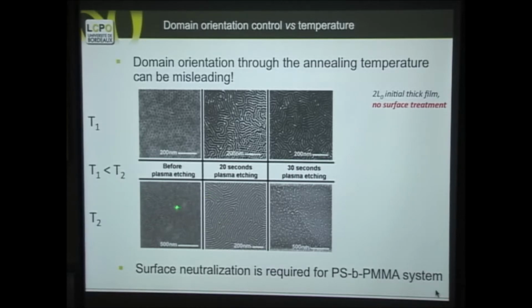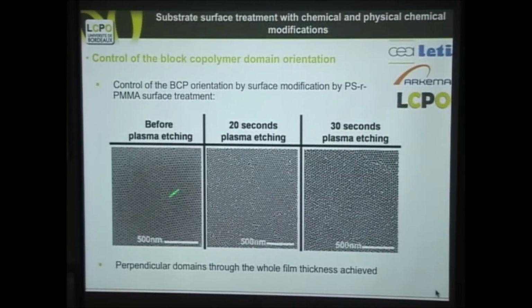So do we have other ways of controlling the way that the cylinders of these microphases are lying down? The dimensions here can be 10 nanometers, either perpendicular or parallel. Well, we can, and we tried by using a copolymer that we treat the surface. This copolymer should be random, meaning that the two monomers are randomly distributed on the chain, and in this way we randomize the interaction parameter of the two blocks with the surface they are going to sit on, so they don't have any preference of one over the other.